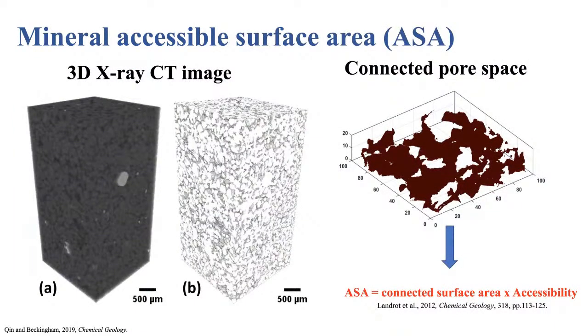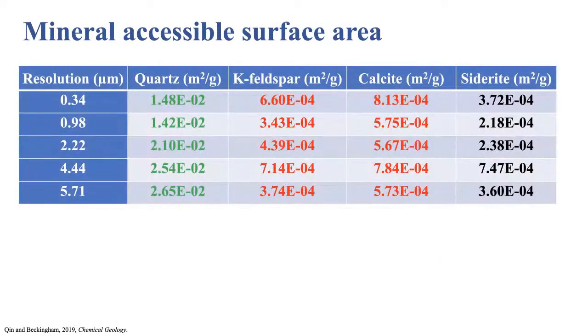To account for connectivity in 3 dimensions, we used X-ray CT imaging, where we extracted cuboids matching with the same total slice surface area as our 2D image, and then quantified the accessible surface area from a series of cuboids and multiplied by accessibility. And so looking at the variations in accessible surface area, we see an increase in quartz accessible surface area with decreasing resolution, and reductions in potassium feldspar and calcite surface areas. But you'll notice these variations are relatively small, just within 1 order of magnitude.